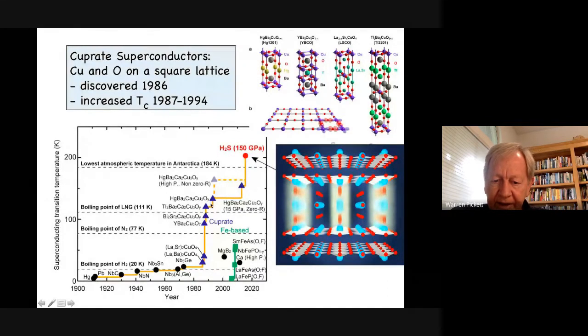Okay. And in the meantime, magnesium diboride was discovered to be superconducting at 40 Kelvin. It's the same sort of superconductor as these, and you see it's almost right on the straight line, by the way. Then in 2008, these iron-based superconductors were discovered, and their TC goes up to 56 Kelvin, as shown here. And I will come back here.